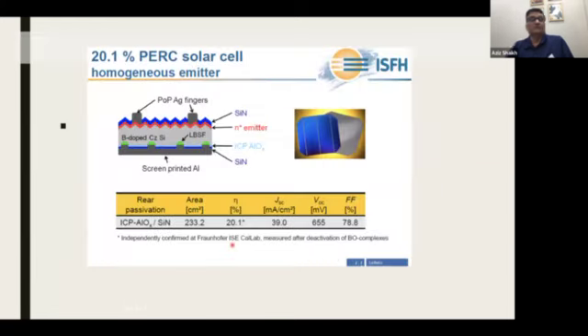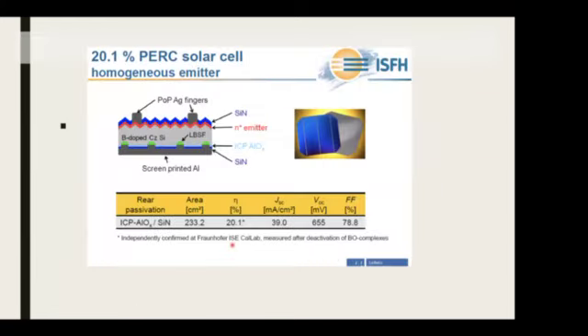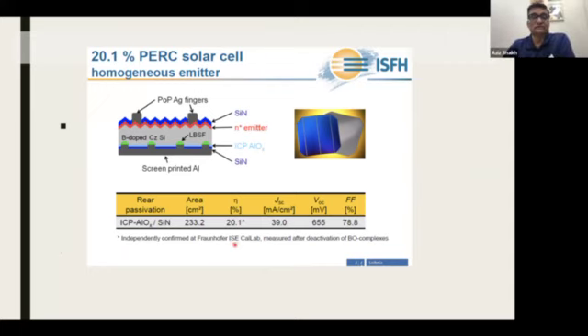Okay, so same information. Now this is the data from ISFH, which basically shows that the efficiency of 20.1% was achieved. Now, if I roll back and I tell you that earlier in the 1980s, the efficiency was 13%. So this is a huge improvement in efficiency. Without BSF, just anti-reflective coating, the efficiency of the CZ cell was 13%. So all the back surface field improvement, back surface passivation improvement, created an efficiency improvement of more than 50% relative. So that is a big factor in terms of reducing the cost.